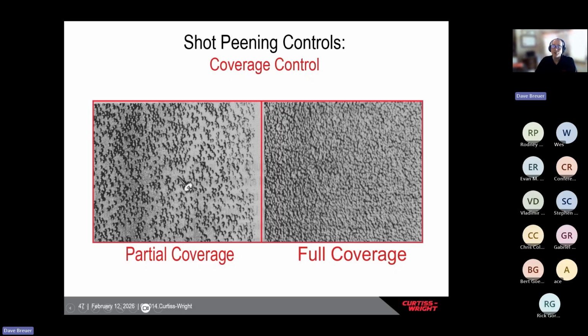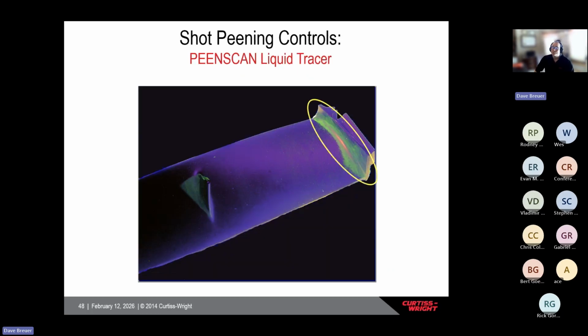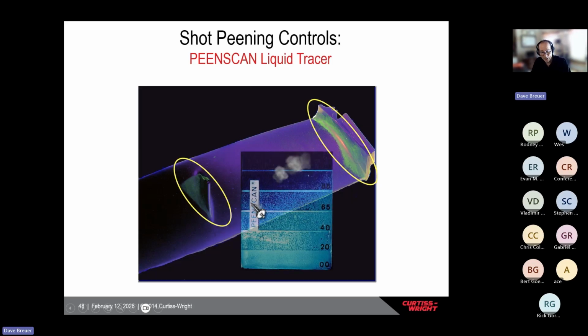And then you would have to identify how long you shot peen that to have complete overlapping dimples for 100% coverage. Some materials like this aluminum, it's easy to see visually. Other times, when you have large amounts of surface area, very hard metal, or the inside of blind holes, it's more challenging.